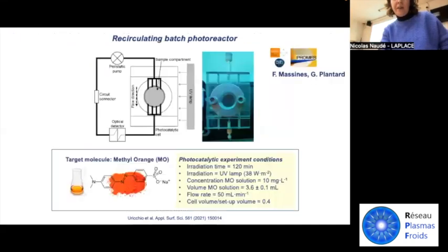And we investigated the photocatalytic activity of these materials using a recirculating batch photoreactor designed and realized by Guy Plantard in PROMES. And we investigated the photocatalytic degradation of methyl orange in recirculating continuous flow conditions.